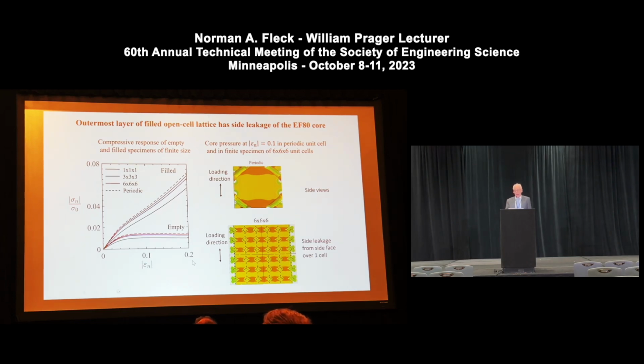This again is for that rubber EF80 core being present. And the physical explanation is that there is a little bit of side leakage out, but only over one cell dimension. And so very quickly, you don't need many cells in order to capture a stabilized response. One can analyze this by a shear-like type process. It's reminiscent of in soil mechanics when people talk about undrained and drained tests, where in the undrained state there's no liquid migration out of the structure, but with time the liquid, whether it's water in the case of the soil, can migrate out the side of the structure and produce a drained response. And here, because the rubber has got a comparable strength to that of the empty lattice, there's not too much side leakage of the rubber.